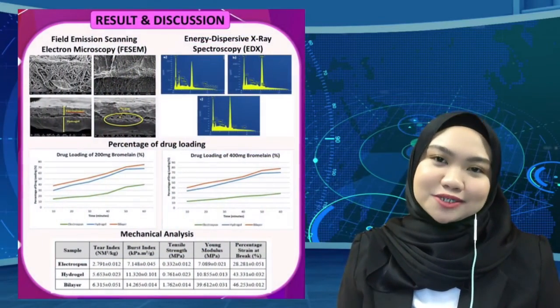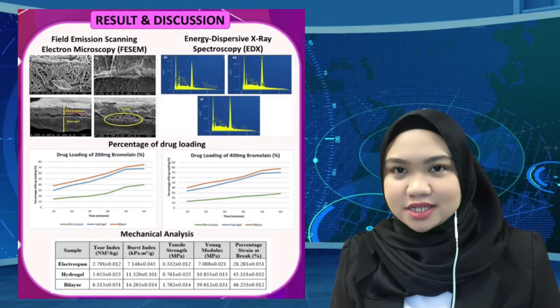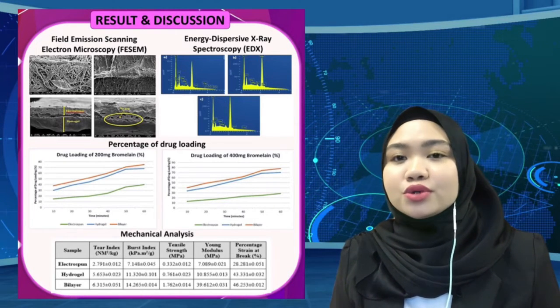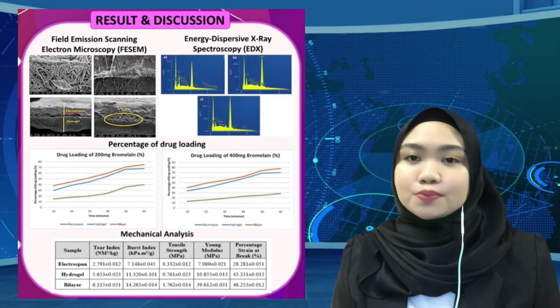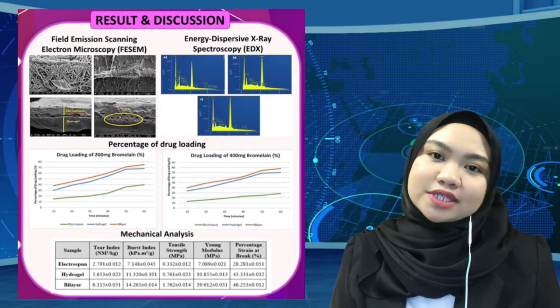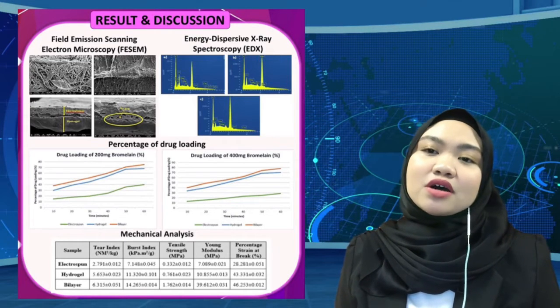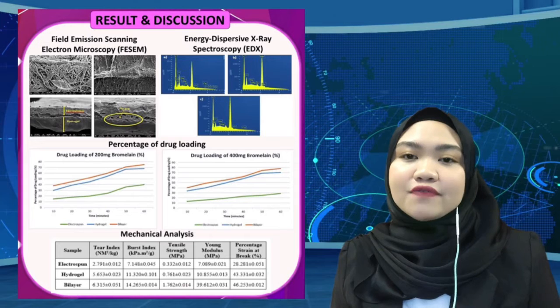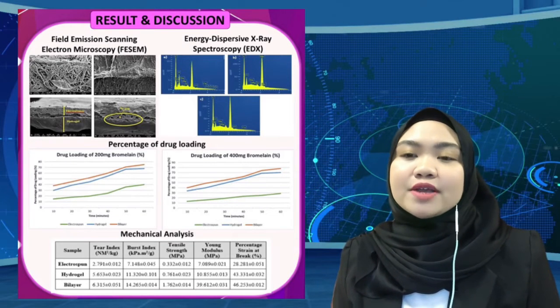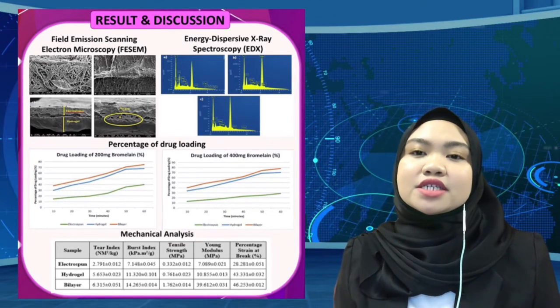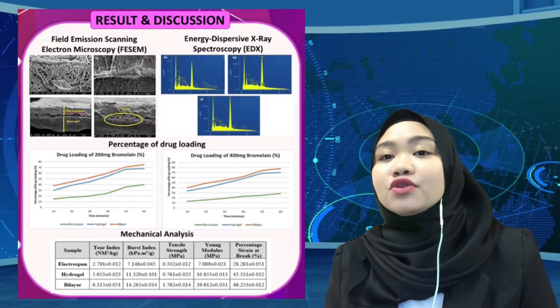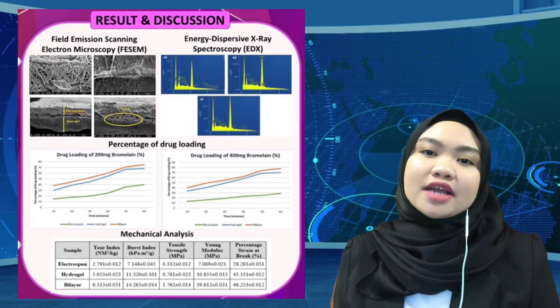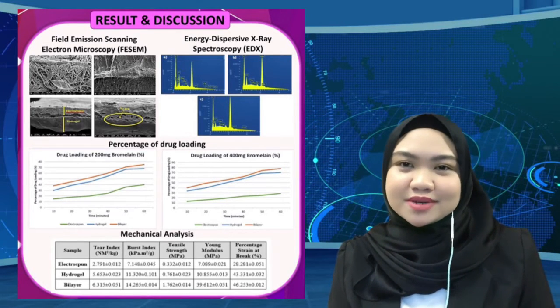So next, we go to the results and discussion part. For the first set, this image shows the cross-sectional composite of electrospun, hydrogel and bilayer composite. The structure of electrospun is observed as discrete and fine fibers. The average fiber diameter of electrospun nanofibers is 100 to 500 nanometer. The image revealed that there is bead formation on the nanofibers.